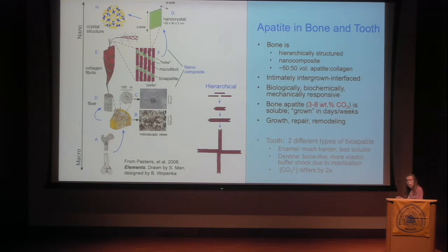That solubility is due to the 3 to 8 weight% carbonate that's substituted into the bioapatite. And note, hydroxyl apatite is not what any chemist would call soluble. This is a very different material. And so the bioapatite has this rapid response time and becomes involved in growth, repair, and remodeling of the bone over time.